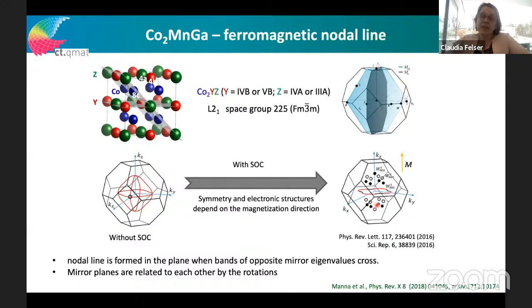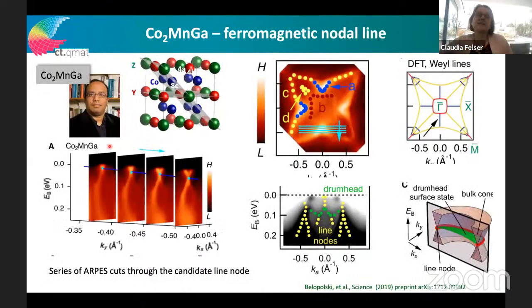But in reality, this material is also a soft magnetic material, so in a photoemission machine we cannot do this. Therefore, our plan was only to see the nodal lines in this compound, and this is exactly what we did together with Hassan. We made films and single crystals, and his team investigated the electronic structure. As you see, here are these crossing points, but they are a series of crossing points. It's a nodal line along this direction, which you can see here.